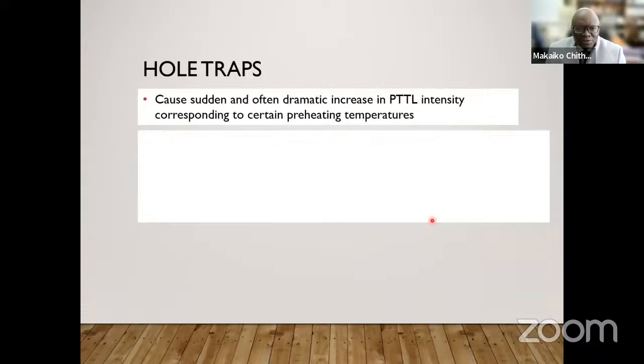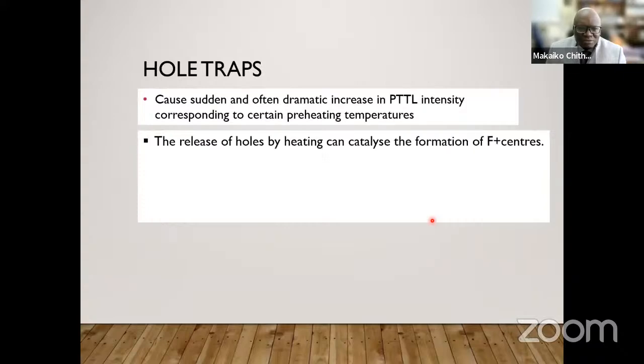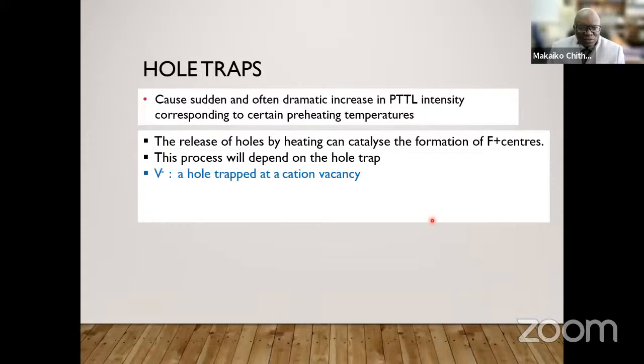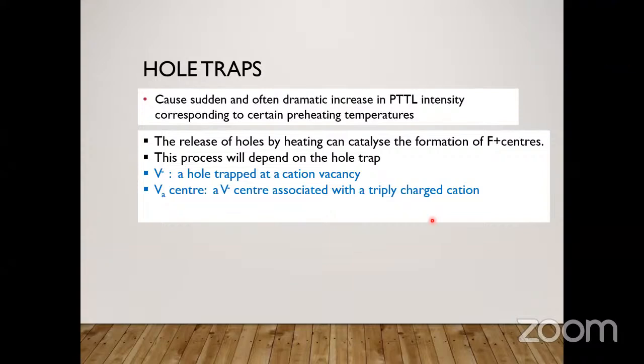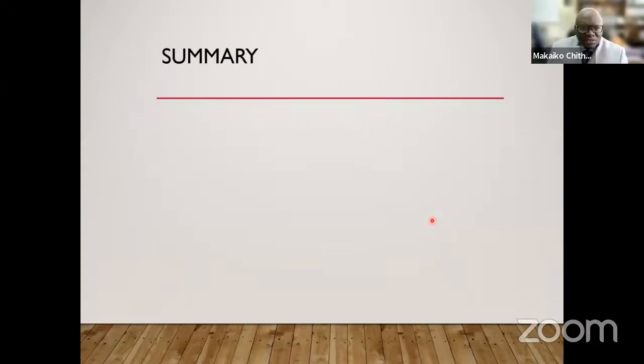Then hole traps, sometimes hole traps cause a sudden and dramatic increase in intensity. I'm not going to say much about this, but in oxides like aluminum oxide, when holes are released, it can catalyze the formation of F+ centers. But this process would depend on the hole trap. The thing with F+ centers is that they can act as recombination centers and can also affect the intensity of your photo transfer. Okay. So there are two examples of hole centers there.